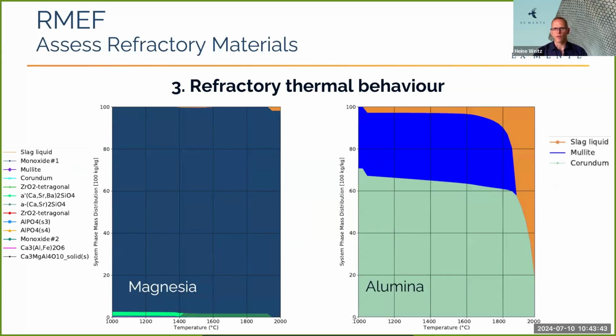So an example of some phase distributions that we've done in the past. On the left, we've got a magnesia refractory, and we've heated that up from 1000 to 2000 degrees Celsius. You can see for the most part, it consists primarily of a monoxide phase, so a periclase type phase. And only at the top right there, you can see a little bit of slag starting to form, but that's at a temperature in excess of 1900 degrees Celsius. So just thermally, this refractory seems to be able to withstand quite high temperatures.